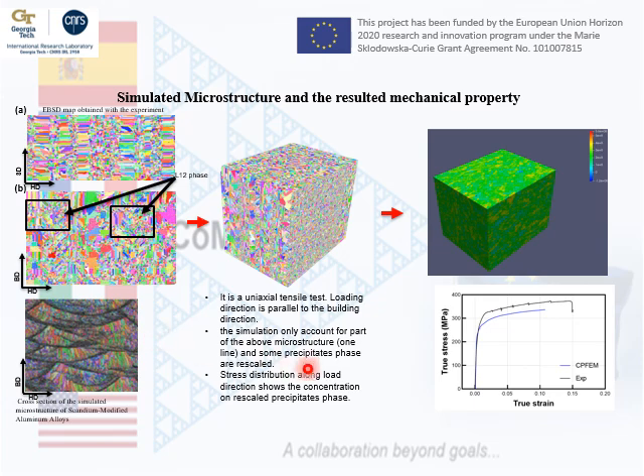Okay, so in any case, to the right we can observe the results of the crystal plasticity model. To begin with, we can observe that there is a deviation between the simulated properties and the experimental ones. Here we are seeing the stress-strain diagram, and the agreement is not really that bad, right? Here we are seeing a deviation of about perhaps 50 megapascal, which is not too bad to say something.